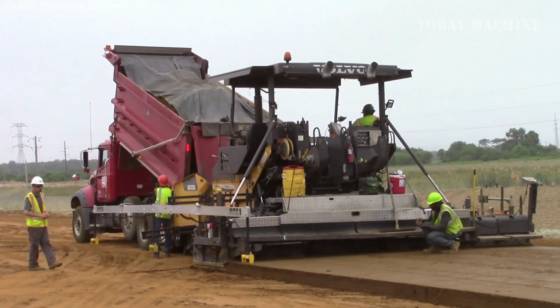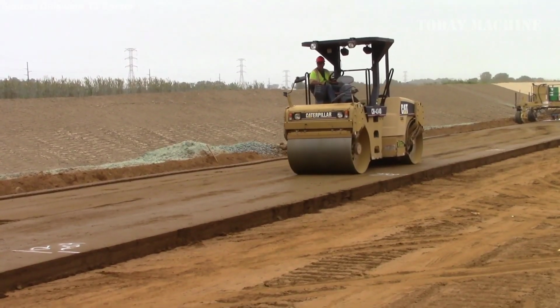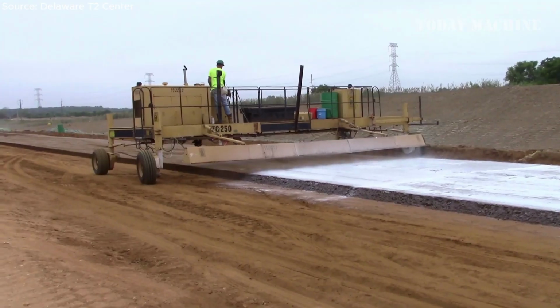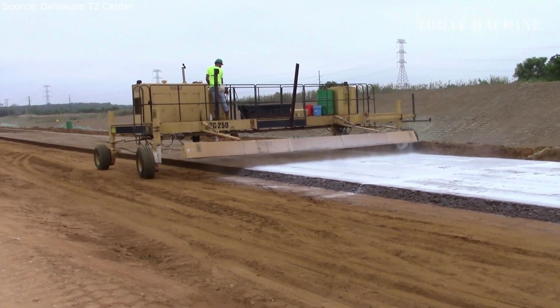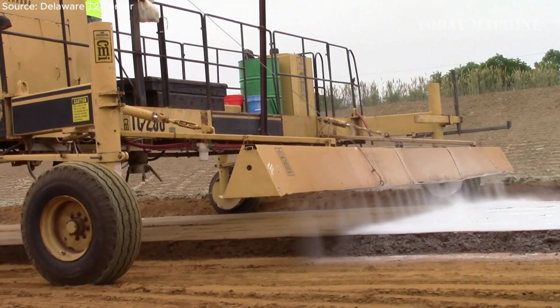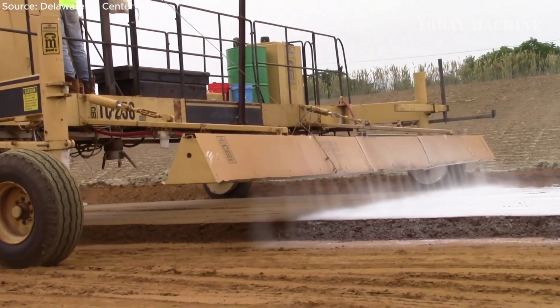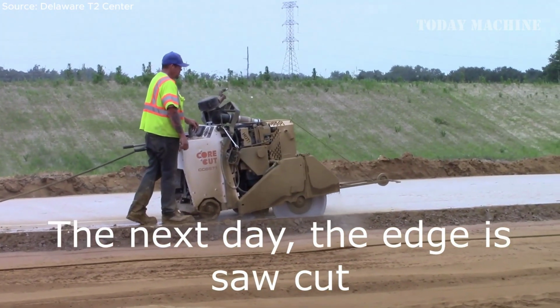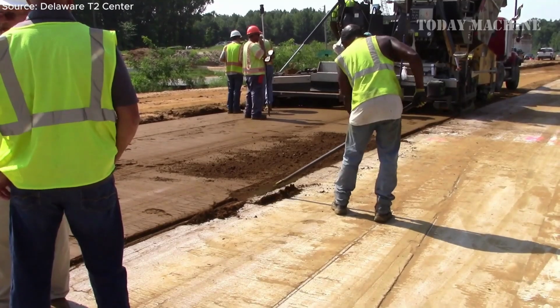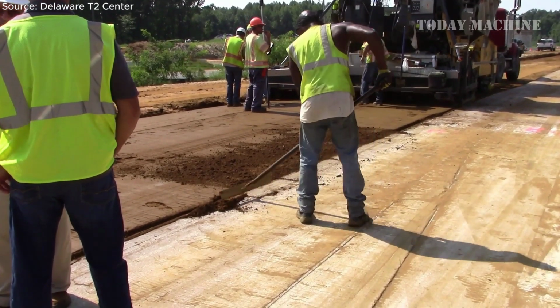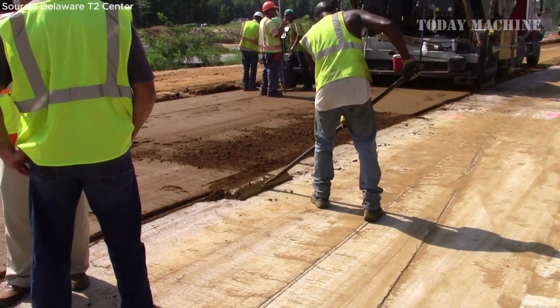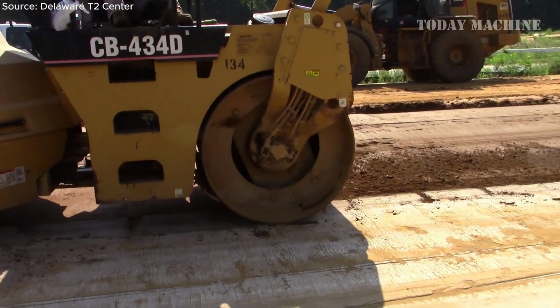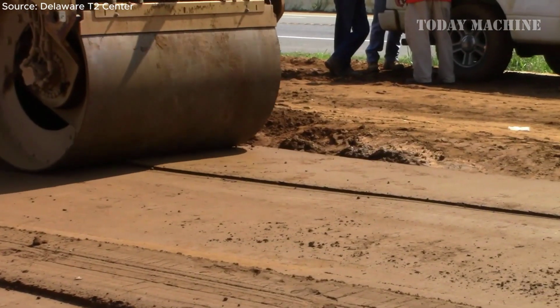Soil cement is formed by blending Type D borrow, Portland cement, and water, then uniformly compacted to achieve 500 psi strength. On US 301, 6 inches of soil cement were placed, compacted in layers, and cured before adding 4 inches of permeable treated base, followed by 12-inch Portland cement concrete pavement.